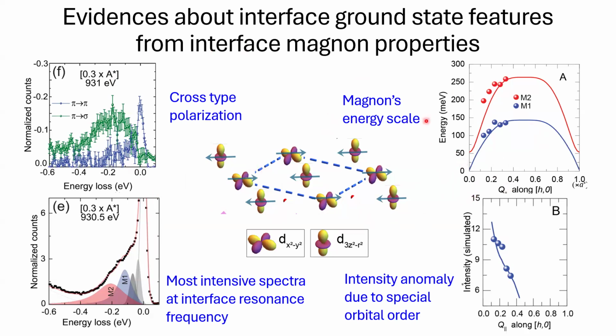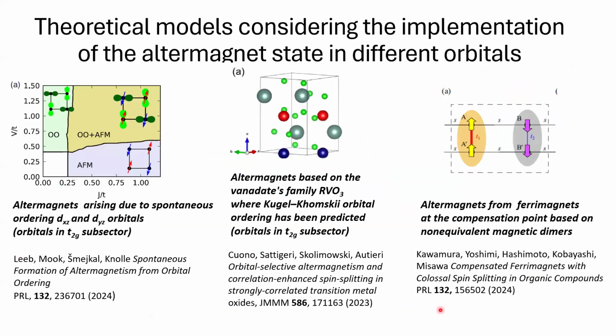So this is the magnon energy scale, cross-type polarization, most intensive spectra at the interface resonance frequency, and an intensity anomaly due to special orbital order. So then it is interesting to consider possible theoretical models for the implementation of the altermagnet state in different orbitals. There is a paper in which an altermagnet arises due to spontaneous ordering of d_xz and d_yz